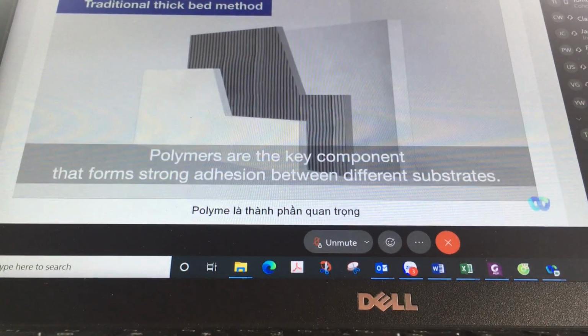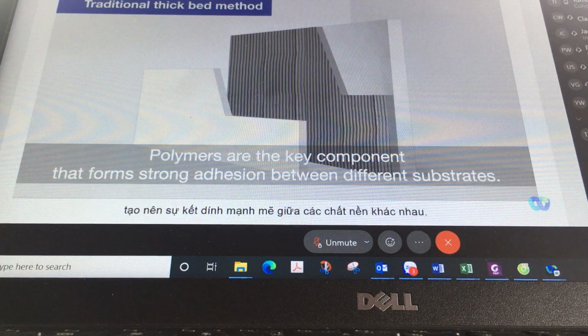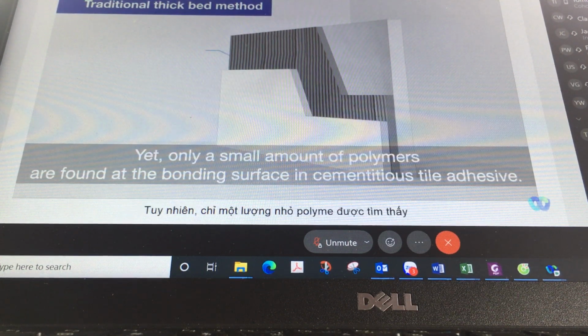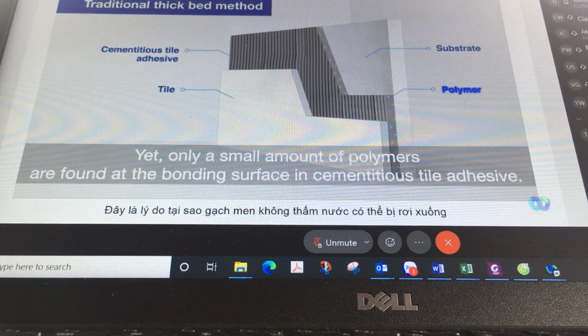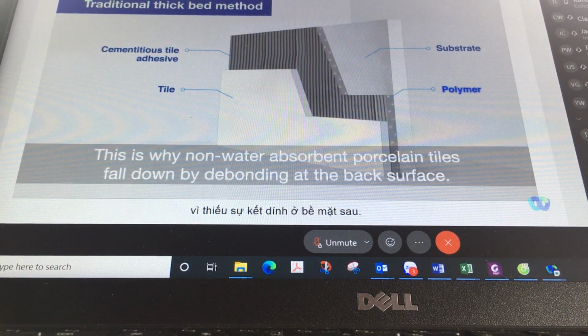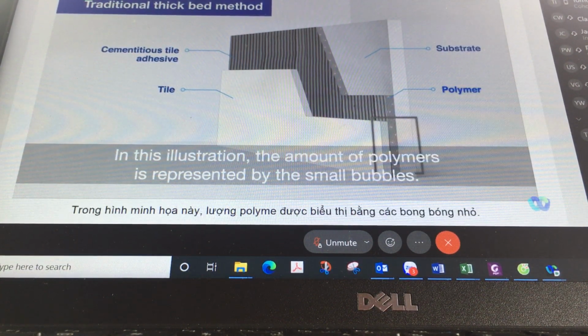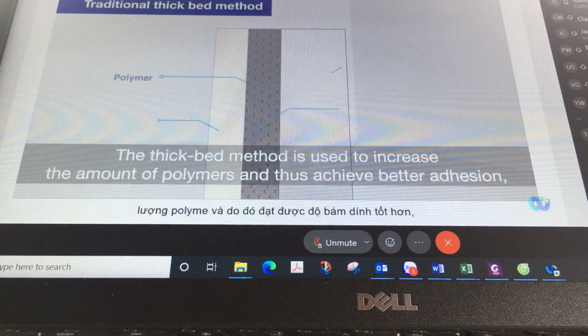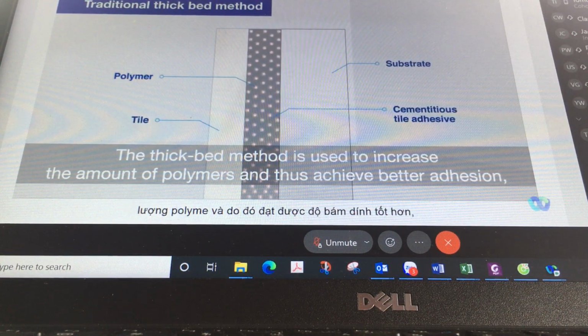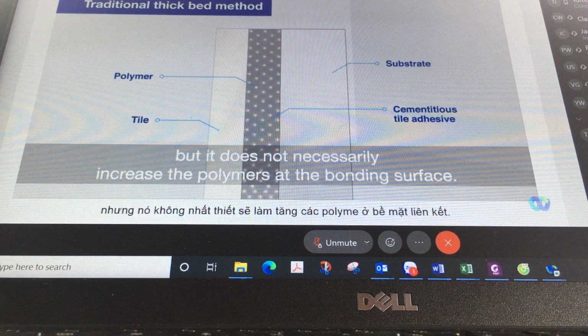Polymers are a key component that forms strong adhesion between different substrates. Yet, only a small amount of polymers are found at the bonding surface in cementitious tile adhesive. This is why non-water absorbing porcelain tiles fall down by debonding at the back surface. In this illustration, the amount of polymers is represented by the small bubbles. The thick bed method is used to increase the amount of polymers and thus achieve better adhesion, but it does not necessarily increase the polymers at the bonding surface.